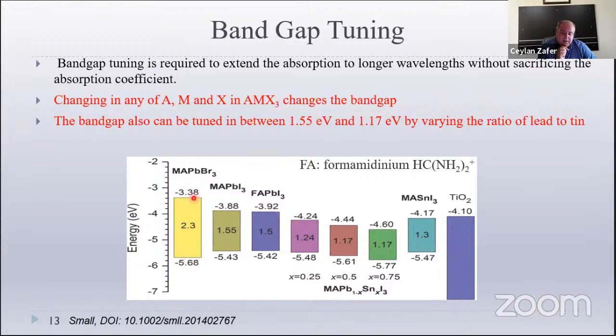with a 2.3 electron volt band gap. It becomes 1.5 by replacing the bromine with the iodide. By changing the cation again, we can slightly play with the energy band alignments, or by changing the center metal, by increasing the content of the tin together with the lead by 25%, 50% and 75%, narrowing the band gap drastically. And that's why the perovskite became very popular in the solar energy conversion area.